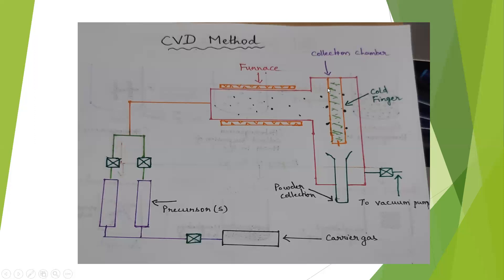When the clusters hit the rotating cold finger substrate, they are deposited on it. So the sequence is: first carrier gas, then precursors, then vapor stream, and finally the nanomaterials as clusters are deposited — that is why the name is chemical vapor deposition. As the process continues, particle deposition also continuously happens. After that, we run a scraper along the cold finger to scrape the deposited powder, which is then collected at the bottom and sent to a compact unit for further analysis.